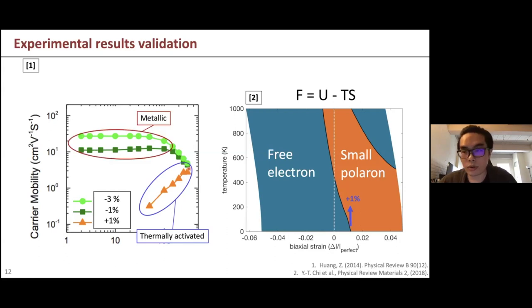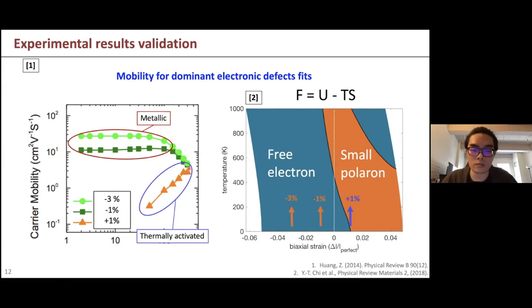For the compressed thin film, it is basically temperature insensitive. If you fit it, it is proportional to the temperature to the power of -1/2 or -3/2, I forgot, but anyway, it is the classic behavior of how free electrons depend on temperature. So here, I'm just showing the mobility for the dominant electronic defects fit between my predominance diagram and their experiment.